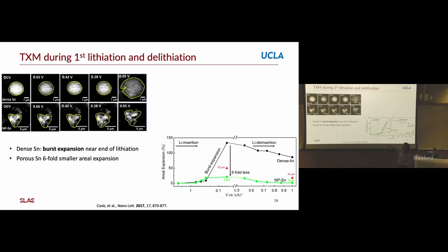This is our initial dense tin on top, and this is just looking at a single particle. We actually did multiple fields of view. Batteries actually cycle very slowly compared to how quickly you can take images, so you can look at lots of different fields of view as you go. For the dense tin, we just have a yellow circle around it to see the volume change more easily. It's actually areal change because it's only a 2D image.